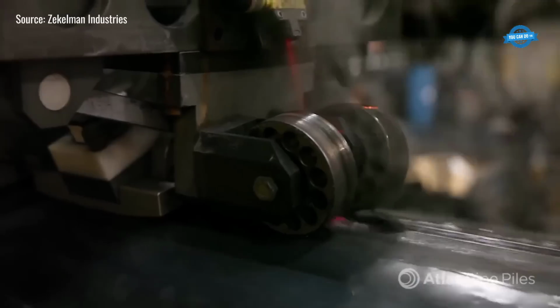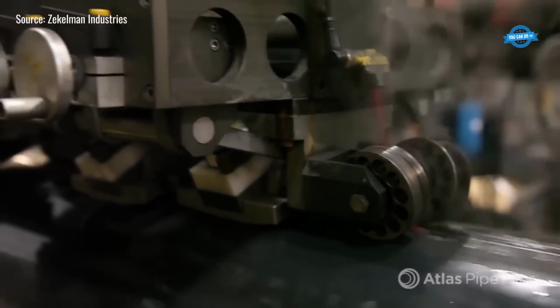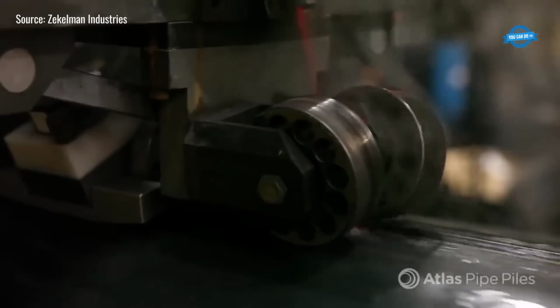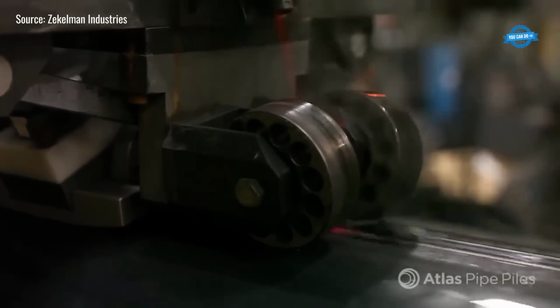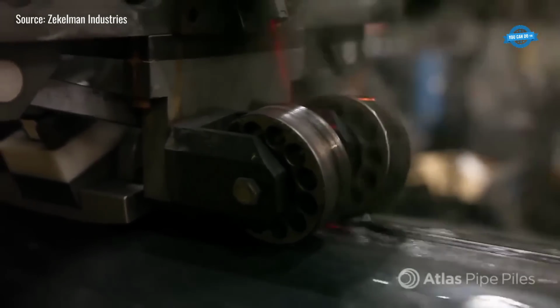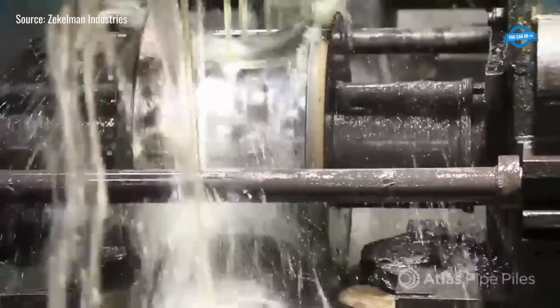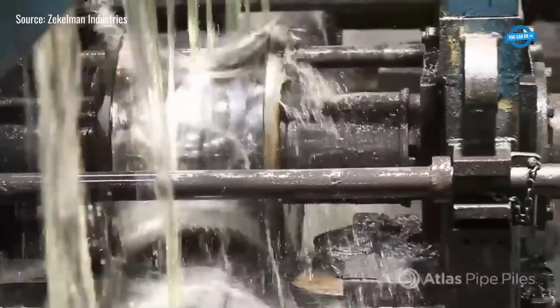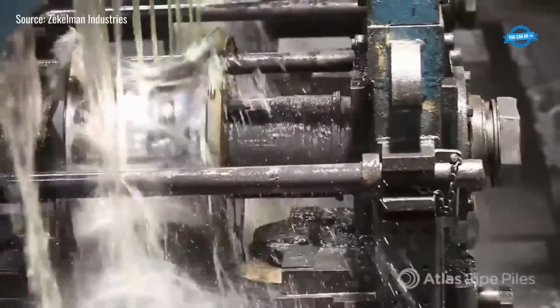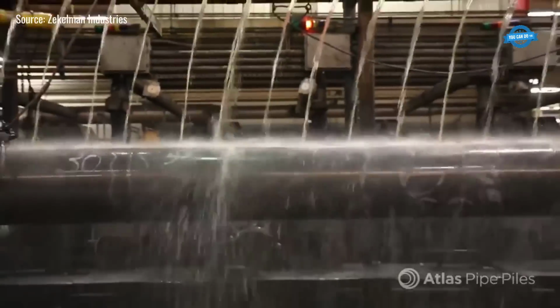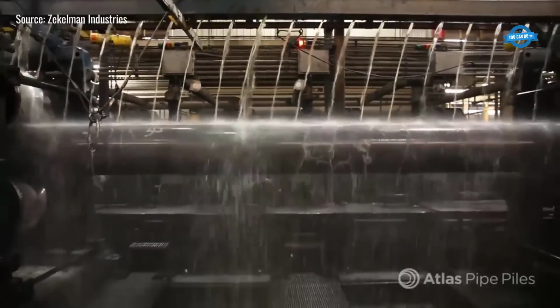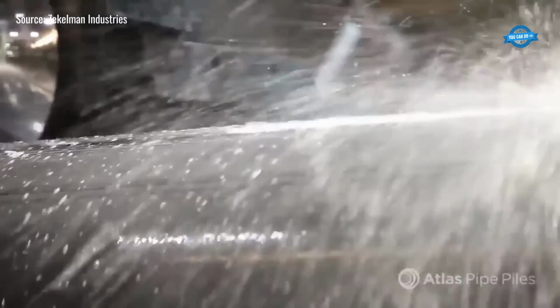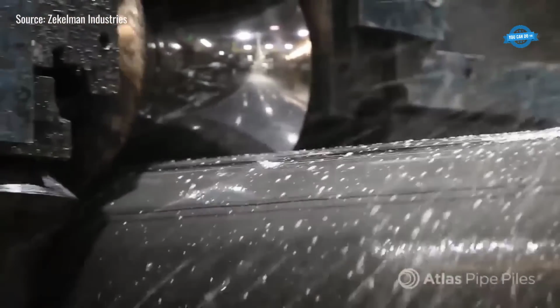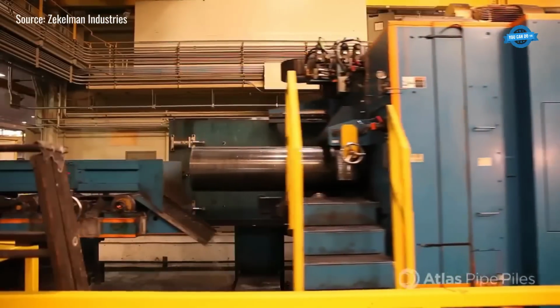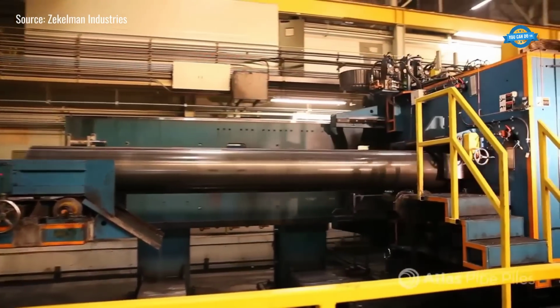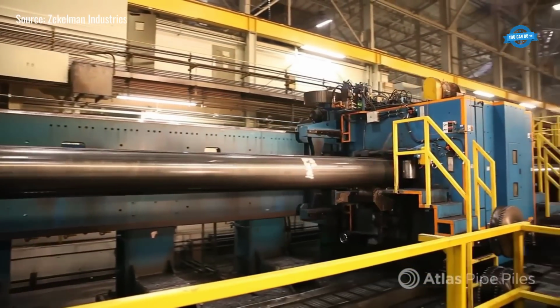The ERW welding process utilizes 2 copper contact shoes to pass an electric current through the strip edges, generating resistance heat up to 2,700 degrees Fahrenheit. This heat creates a longitudinal weld as the pipe moves at speeds of up to 120 feet per minute. Any excess material from the seam is removed using a scarf cutter, resulting in a smooth, nearly invisible weld. The pipe is then ironed while still hot to achieve the required diameter and dimensions for installation.